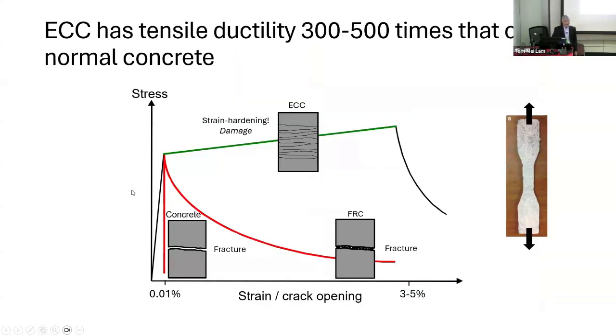Okay, so if you look from the viewpoint of a tensile stress strain curve, let's say a specimen loaded in direct tension, a piece of concrete will behave like this: elastic, and then suddenly the crack forms and the load drops to zero. Okay, so it completely gives up load carrying capacity. If you put some fibers, which has been around for some years, fiber reinforced concrete, you have this tail here. So you have tension softening where a crack opens up, and as it opens, fibers bridge across, and they often break or pull out, so the load carrying capacity continues to drop, okay, while the crack opens up larger and larger.